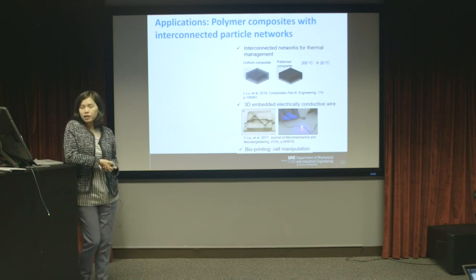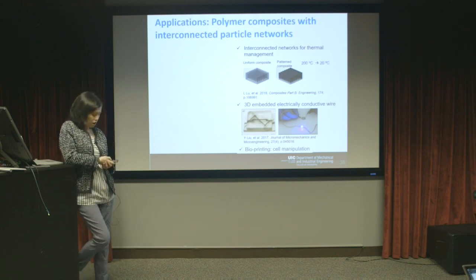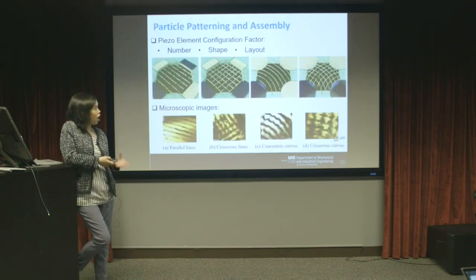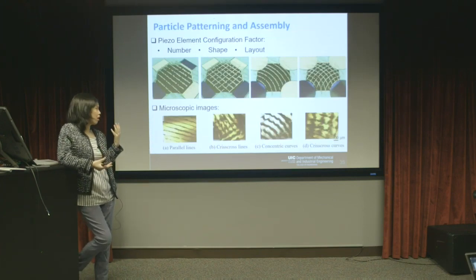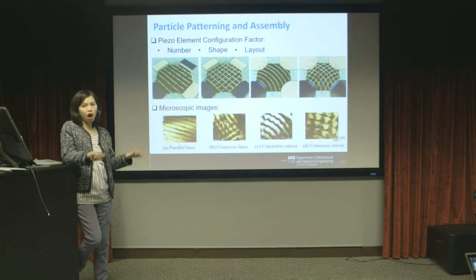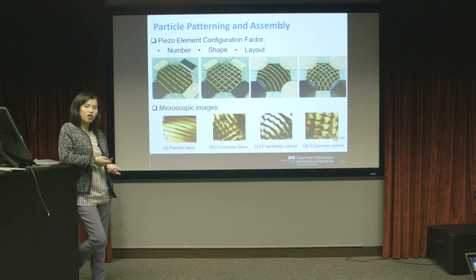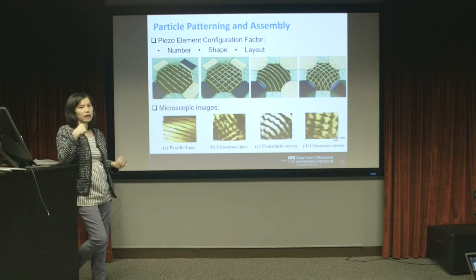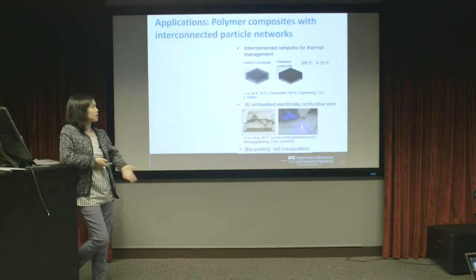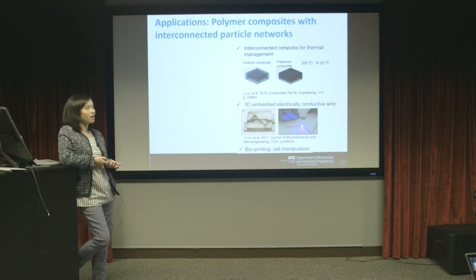As for applications of this process, instead of complicated patterns, it can only achieve parallel lines or parallel curves, or just a combination of them. You cannot achieve complicated patterns such as the letters, as you've seen in the magnetic field assisted process. So this process's application is more about patterning particles into networks or line structures.